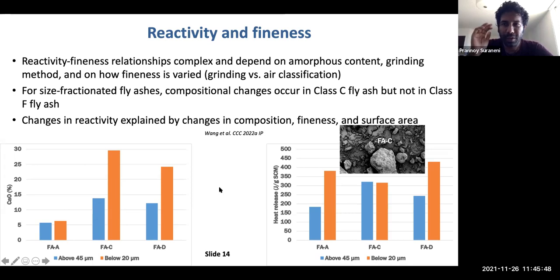So if you're talking about size fractionation, you want to be very careful because you can't just study 1 fly ash or 2 fly ashes and generalize. We actually studied like 6 fly ashes and we found 3 distinct types of behavior. We are again writing this up, but this just shows you that size fractionation leads to some really interesting but complex changes in composition, fineness, and therefore reactivity.